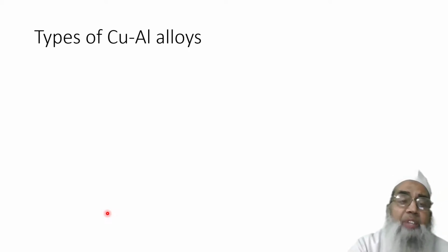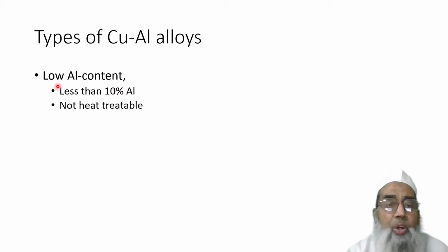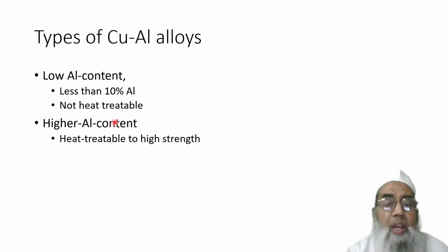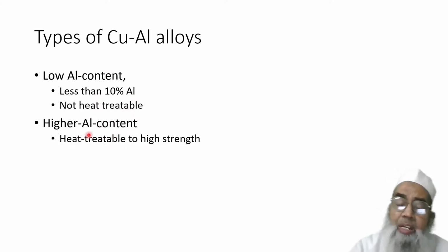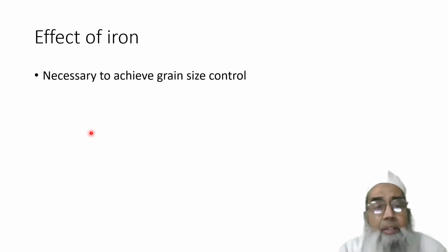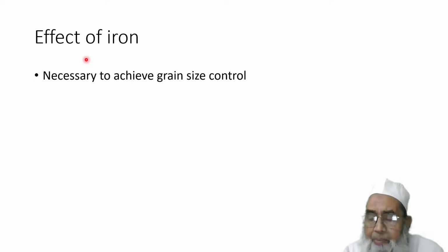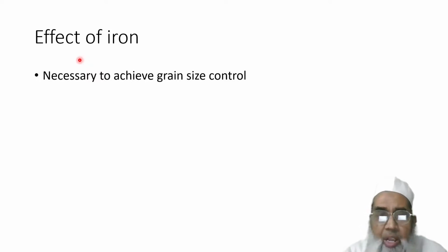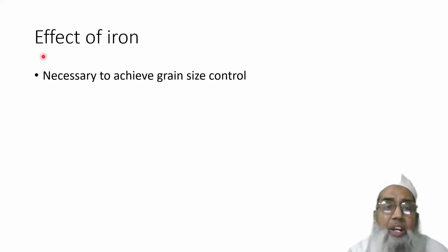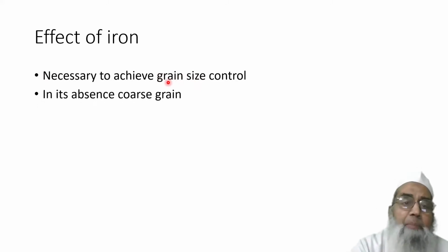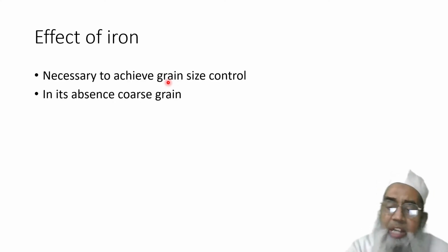Now there are different types of copper aluminium alloys. Low aluminium content, that is less than 10%, cannot be heat treated. However, higher aluminum content, more than 10%, can be heat treated to high strength. Now the effect of iron. Iron is also there. It is always picked up, because sometimes we use steel pots, and while using these steel pots, iron gets picked up, and it is necessary to achieve fine grain size. This iron facilitates control of the grain size. But in its absence, coarse grain is obtained.